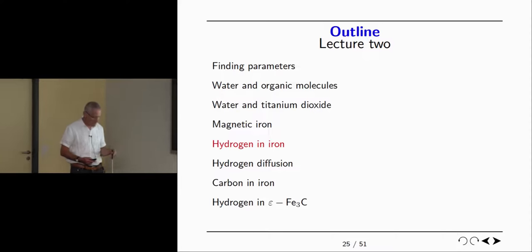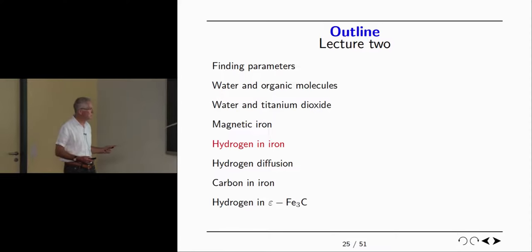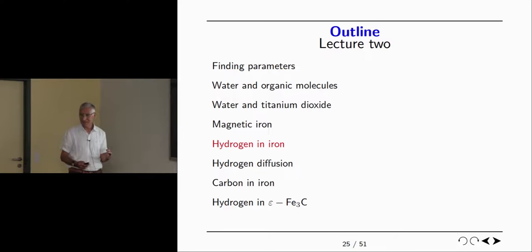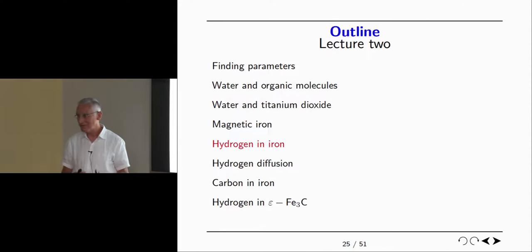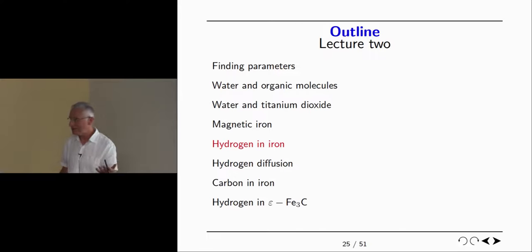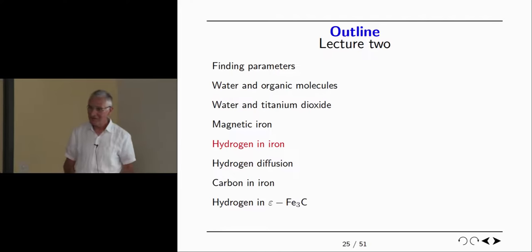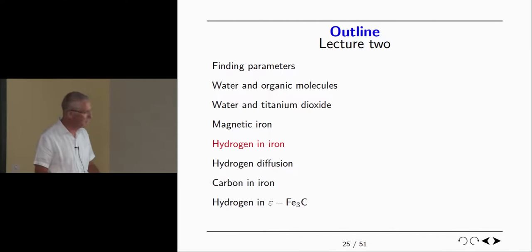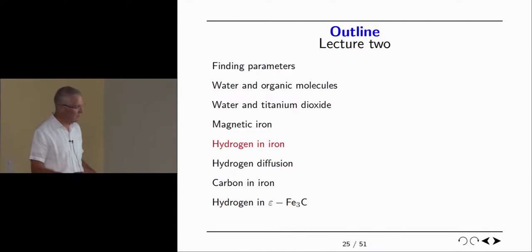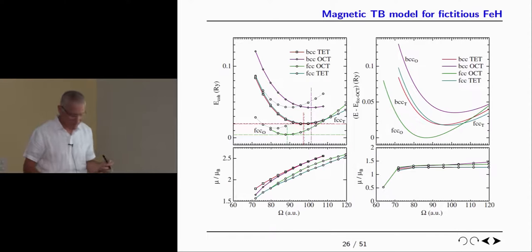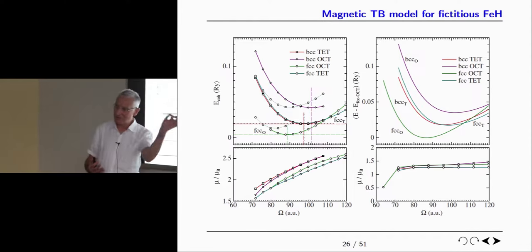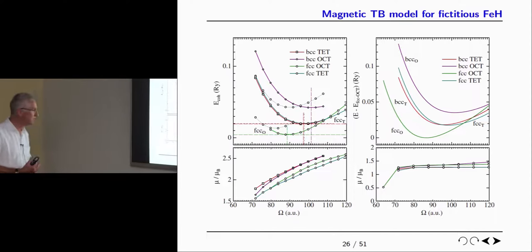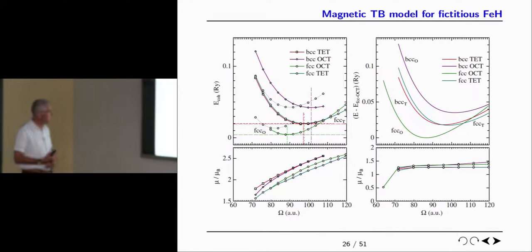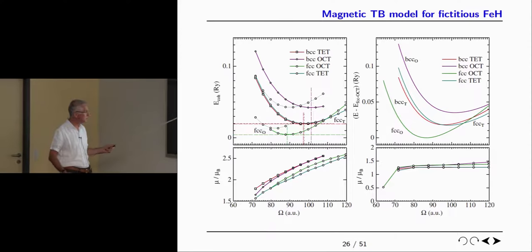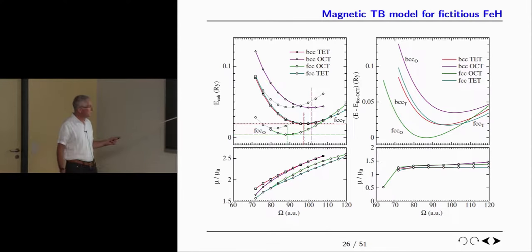The principle that I try to work on is that if I now want to make a model for hydrogen in iron, I don't go messing with the iron parameters. They're fixed. We have a model for iron and I want to use it, and I don't want to change it because of the embarrassment of hydrogen not working. So we live with the parameters that we have for iron, and we simply seek now some hopping integrals for the s electron on the hydrogen to the d and s orbitals on the iron atoms, and some pair potentials. And I actually worked with just five quantities to fit to.